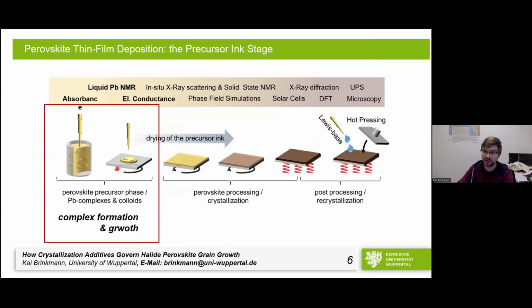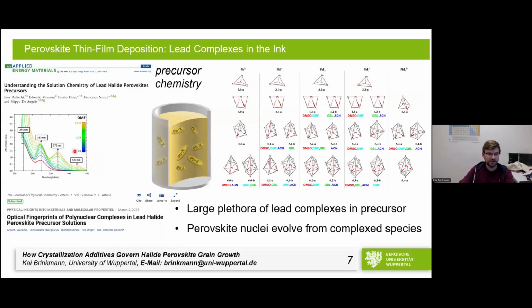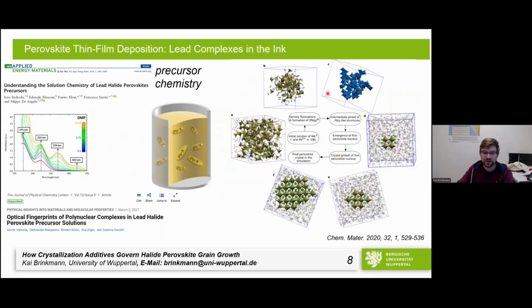There's a lot of very, very good work on what is actually going on with the precursors. So we already know that the solvent will be forming complexes with the lead halides, possibly also with the methylammonium or the A-site cation, but what you can actually nicely probe is the lead halide. There's a huge amount of different complexes that can be there. And in the next level of complexity, these complexes have often been taken as the root cause for why grains are large or small. Basically, these are the nuclei, and they define how many nuclei we have in the precursor, and then we spin coat them, dry them, and then they grow. This would explain why we got the same grain size every single time.